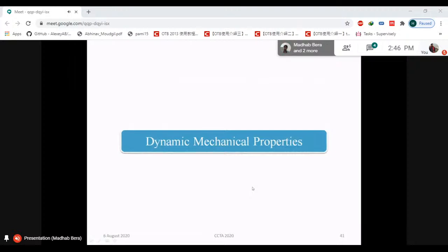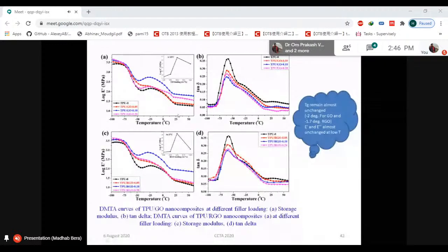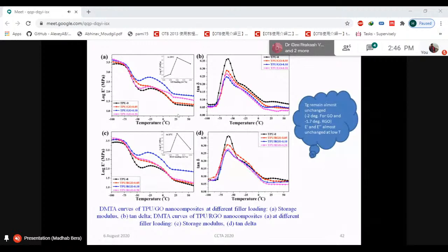Now, dynamic mechanical properties. These are actually very important for the use of this material over a long temperature range. Here we can see that the dynamic mechanical properties of this material are affected very little if we go below room temperature or below 0 degree. Because of this, the polyurethane nanocomposite material can be used in environments where the temperature is below room temperature. The glass transition temperature of the soft segment is affected very little. In case of GO, it is affected 2 degrees, but in case of RGO, it is affected only 1.7 degrees, and the modulus is almost unchanged. So the material can be used for cryogenic applications also.